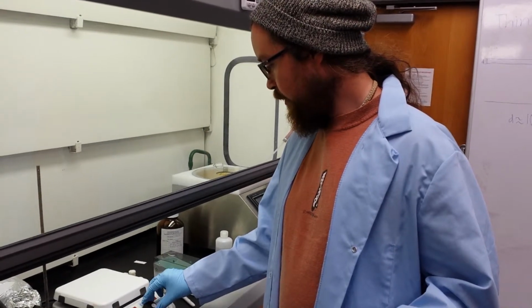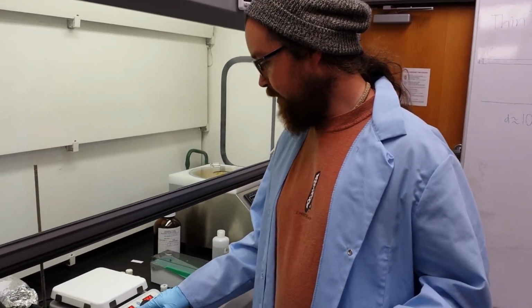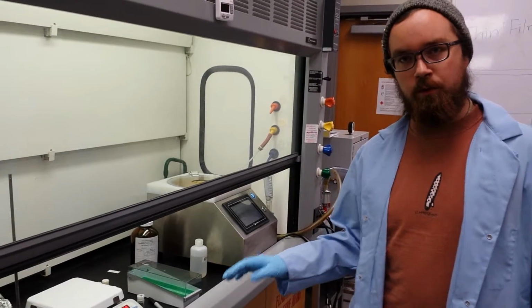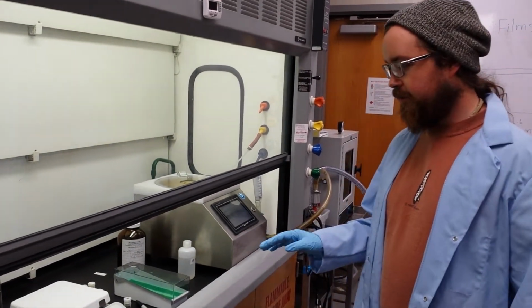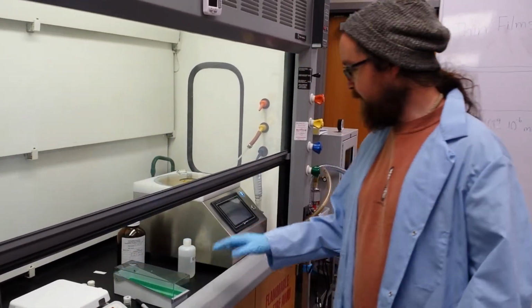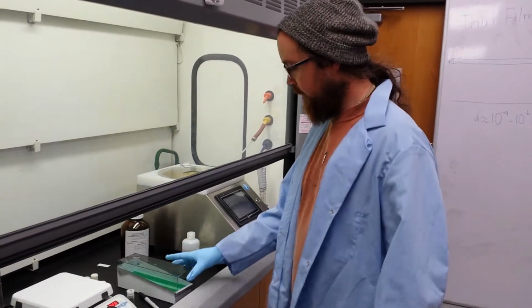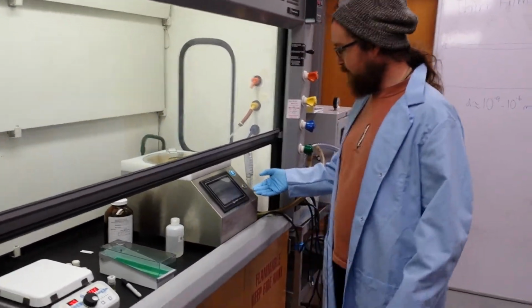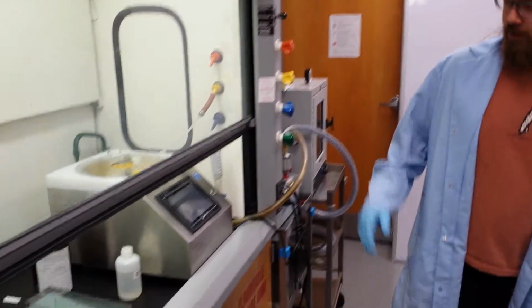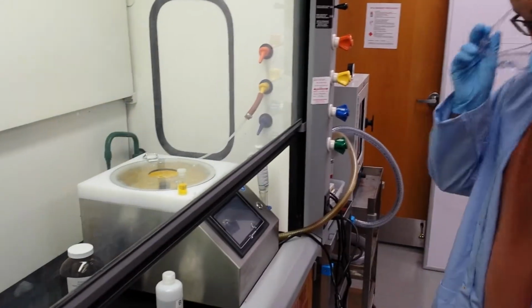So right now we're going to set this to 75 Celsius, which is just below the boiling point of our solvent, and that'll allow us to make the film and not destroy the surface. So to actually make the film, we come over here to what's called our spin coater, which is the machine that we're going to use to deposit the film.